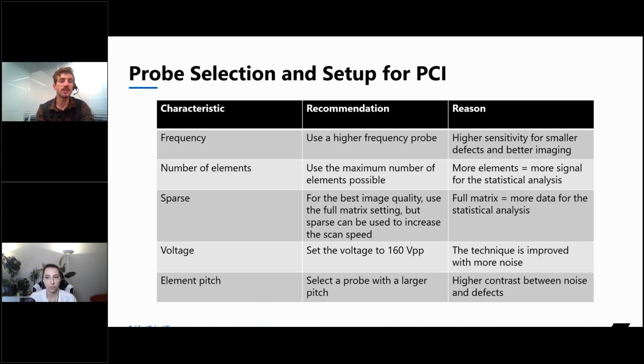So as far as our probe selection goes, frequency, we want to move into a higher frequency probe. Like I said, generally doubling the frequency is a good starting point. The number of elements, using the maximum elements possible. The reason for this is with the statistical analysis that we're doing, the more data we have, the greater contrast there will be between background noise and coherent signal.